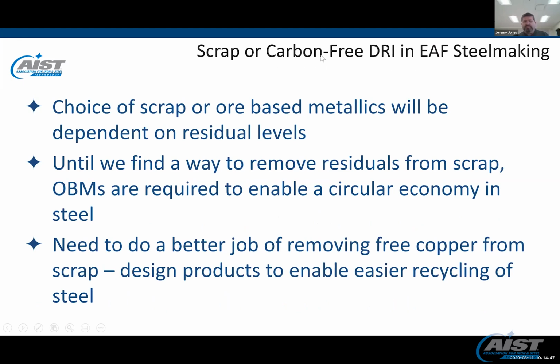With respect to scrap or carbon-free DRI, the choice is really a function of what you're making and what you have available. Until we find a way to remove residuals from scrap, ore-based metallics are going to be required to enable a circular economy in steel. If you look at the projections in the developed world, the generation of prompt scrap is projected to stay fairly constant through to about 2050, while the amount of obsolete scrap that's coming back into the scrap supply is growing quite considerably. So we'll have to figure out how we use that.